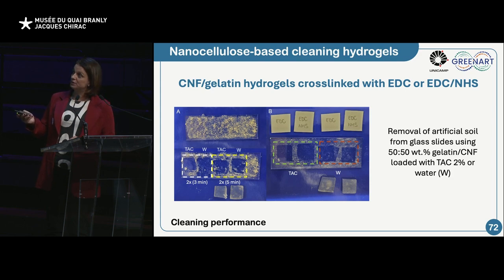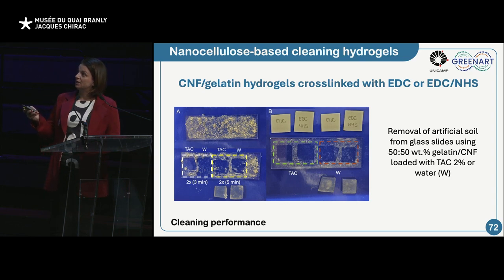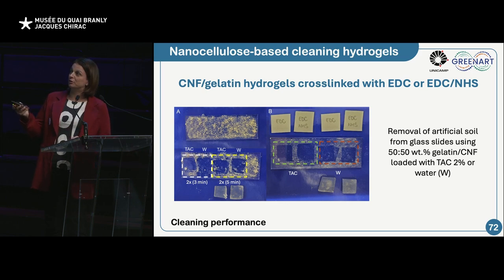We tested the cleaning performance of the gel. So this is a very simple test using glass slides covered with artificial soil, and we tested how the gels could be used to remove this dust. Here, it's just a glass slide covered with dust. Here we have two different fluids that we use to fill the gels. This is TAC, triammonium citrate, a surfactant. And this is water. So in every case, using 2 times we could remove the dust. Here are just the different gels. This is important for us, maybe not so much for you, but you see which kind of cross-linking we are using here.